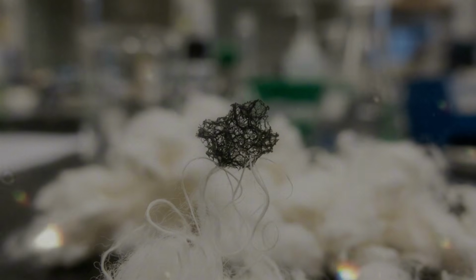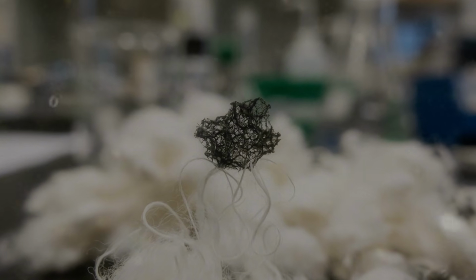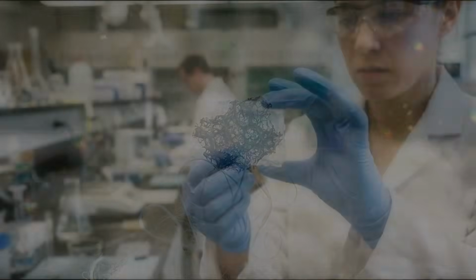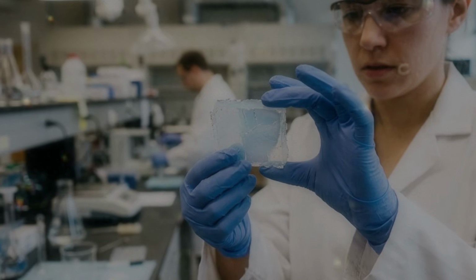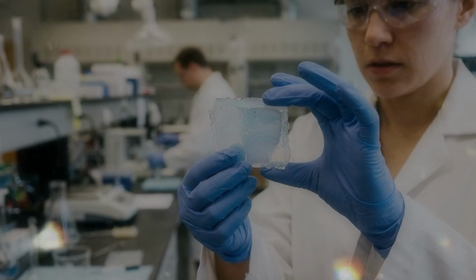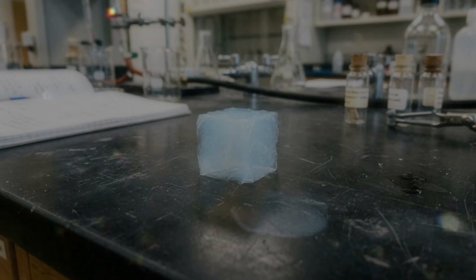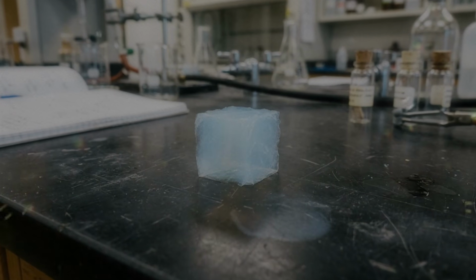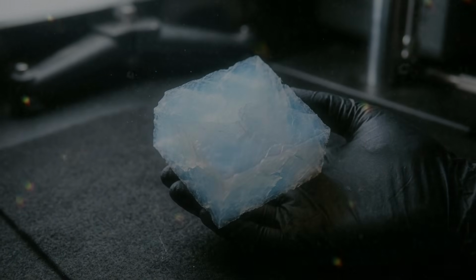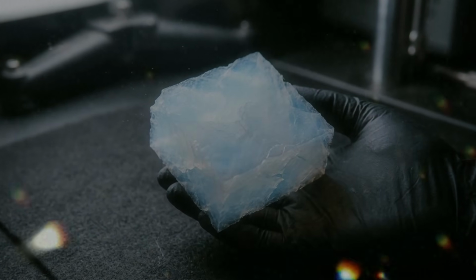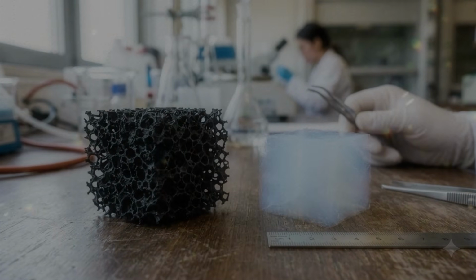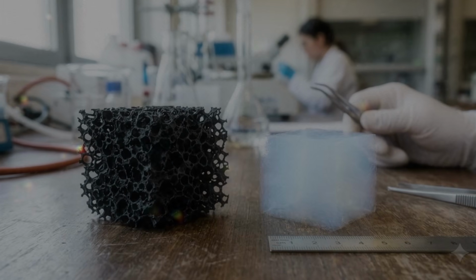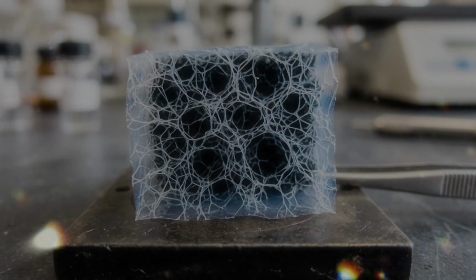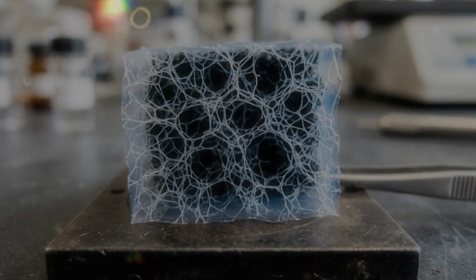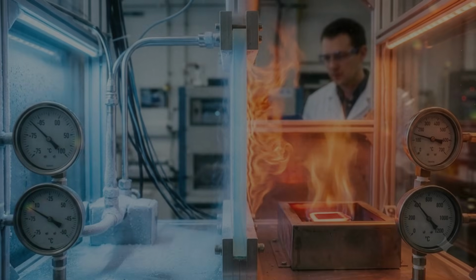Continuous production could make a major difference. Instead of preparing one sealed container at a time, a liquid mixture might be spread onto a moving fabric, allowed to form a gel, washed, dried, and rolled for transport. Fibers would support the structure throughout the process. The result would not look like the clear blue aerogel often shown in photographs. It might look like an ordinary grey sheet, which is often what useful technology looks like after the photographers have gone home. Printing methods offer another route. A thick liquid containing silica particles, graphene oxide, cellulose, polymers, or other building blocks can be deposited in planned patterns.